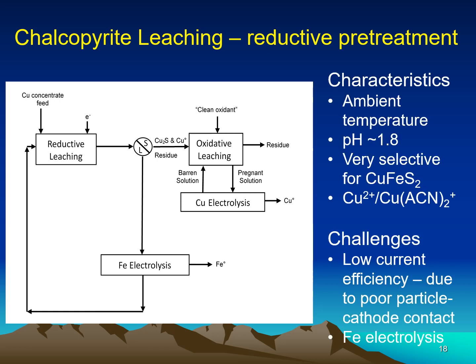The characteristics of this process are ambient temperature, pH near 1.8. It's very selective for chalcopyrite. And the interesting part here is the oxidative leaching stage uses the redox pair of the cupric ion and cuprous acetonitrile complex. The challenges are that there's quite a low current efficiency, especially when we have poor